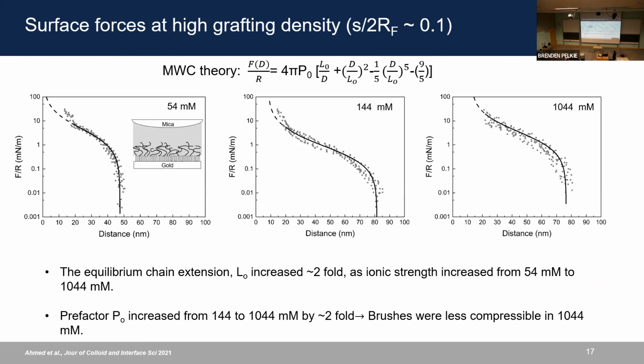1044 millimolar salt concentration. And when we compared the two higher salt concentrations, we see that the range of the repulsive barrier remains the same, but the surface forces that were measured were higher. So the brushes were less compressible at the highest ionic strength.